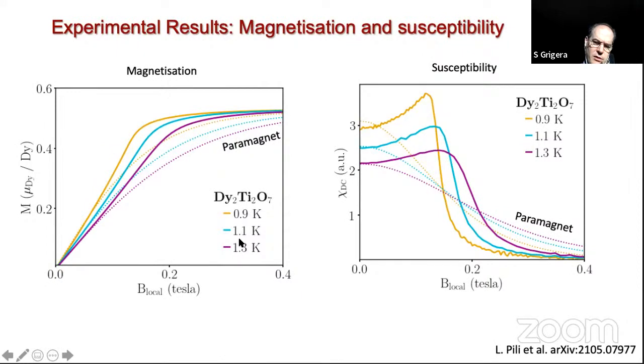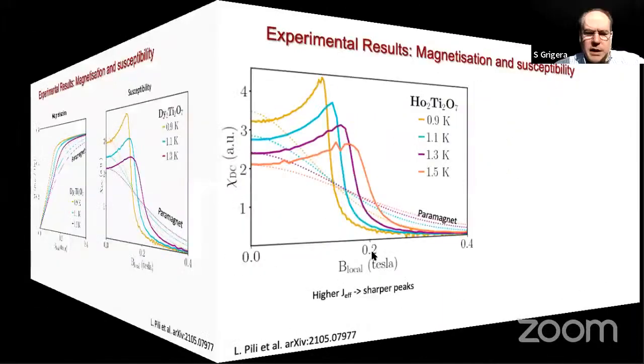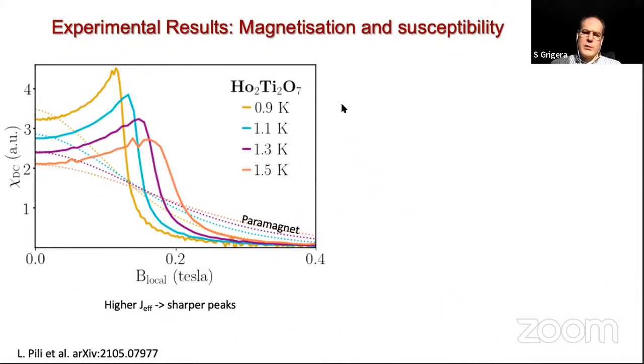because the temperature is not that low, and the reason why the temperature is not very low is because the system, in addition to all the interactions, has dipolar interactions. You see that these are big moments. So it freezes at very low temperatures. So you need to be working in this regime where the temperature is low enough that you have this type of ground state, but it's not low enough that you don't have single spin flips. Okay, and this is how the susceptibility looks. And you see again that you have something which is very anisotropic, in the sense that the low temperature phase looks very different from the high field phase. And this is the same measurement taken now in holmium titanate.